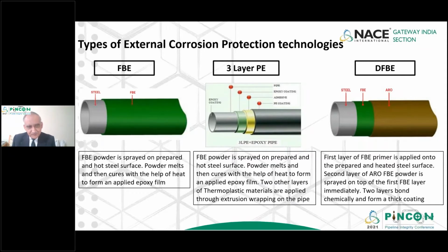When we come to Europe and the Middle East, there is another trend, where a three-layer polyethylene coating system is being applied. And the three-layer polyethylene coating system was introduced after FBE was introduced. What was the reason for that? The fundamental thing is that pieces of pipe are coated in a factory, and then they are transported by truck to the construction site. During this truck drive, the pipes have a lot of bumpy rides, in which the pipes impact each other. And during handling, the pipes are taken through the powered crane.